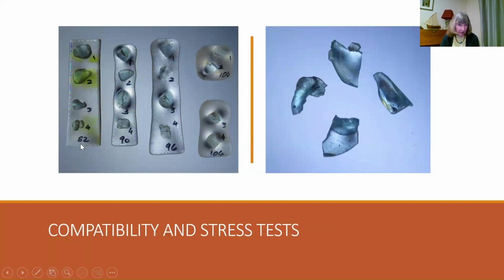Here, this is the very hard glass, and there's no halos at all, because you can just about see there are cracks. The Roman glass was so different to this float glass that the stress took over and it cracked. So once it cracks, the stress is released and you don't see a glow. This is just discoloration. This looks pretty close.